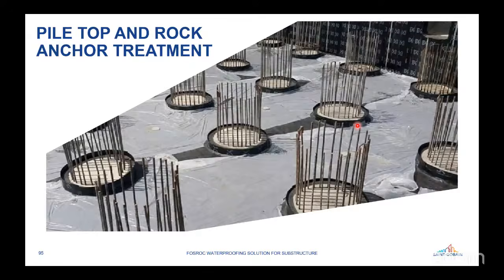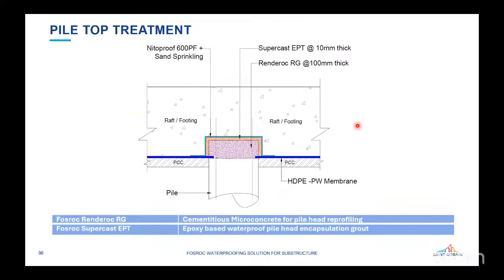So coming to another treatment what normally we do in substructure waterproofing is the pile top treatment, because certain types of foundation design need the pile foundation. So on that there is a PCC layer with the pile protruding from that area. This is a very important point in any waterproofing system that needs to be properly sealed. So here the blue line you're seeing is the waterproofing membrane which will be taken up to the pile head level, and then the reprofiling of the pile is done with a cementitious micro concrete, and then there is another layer of an epoxy grout which will be applied over it. This is to prevent any kind of water ingress to the reinforcement part.